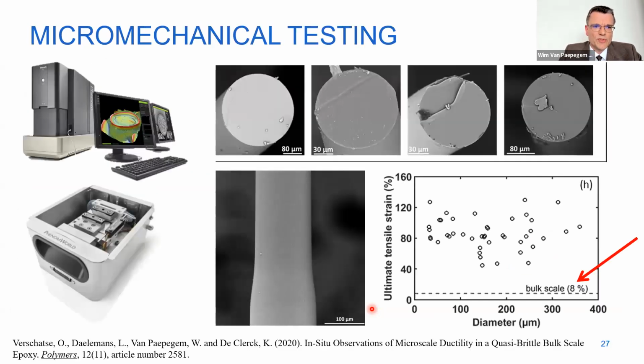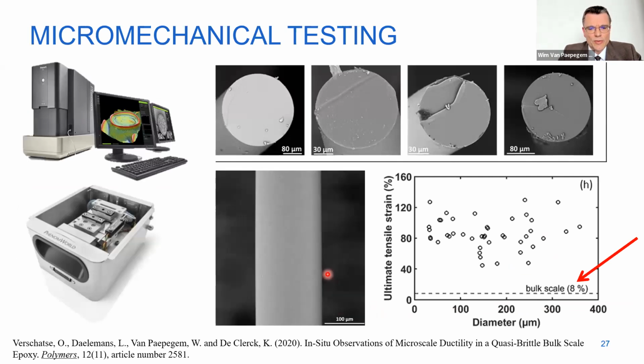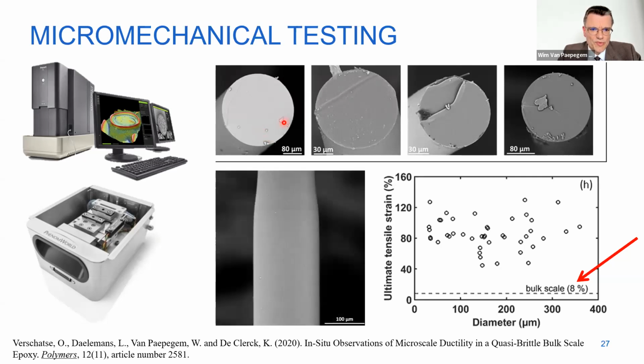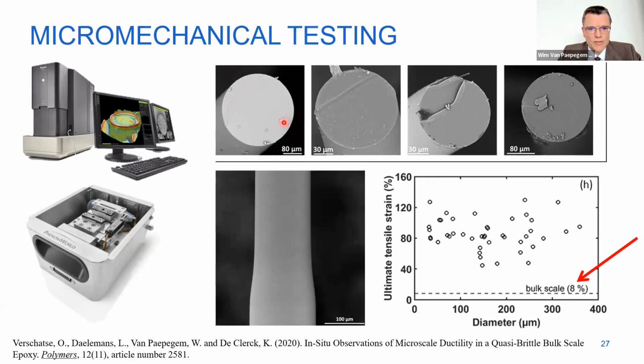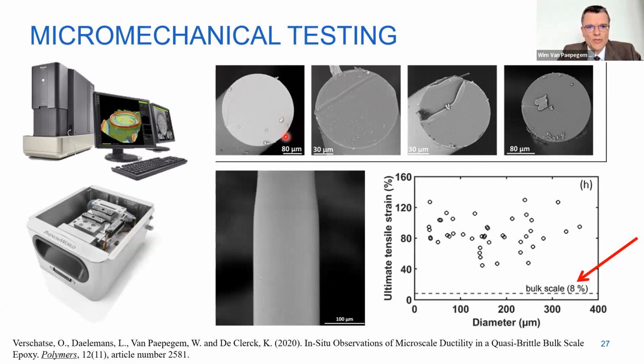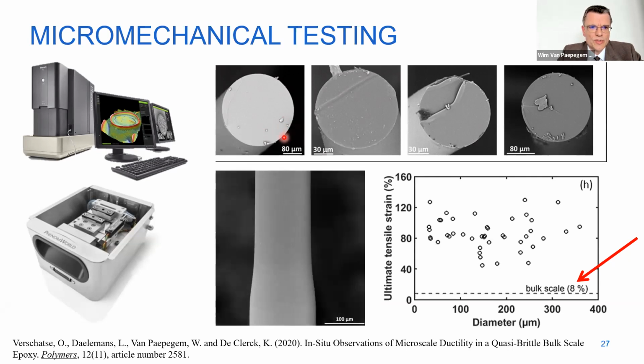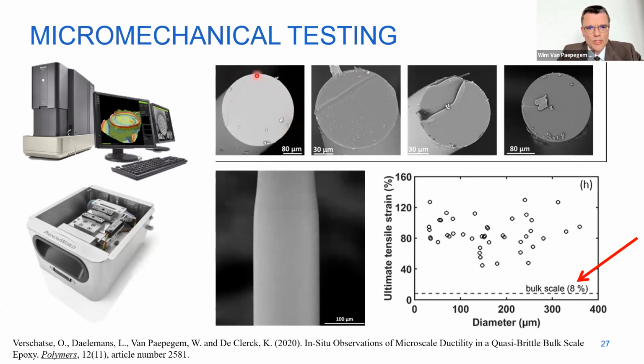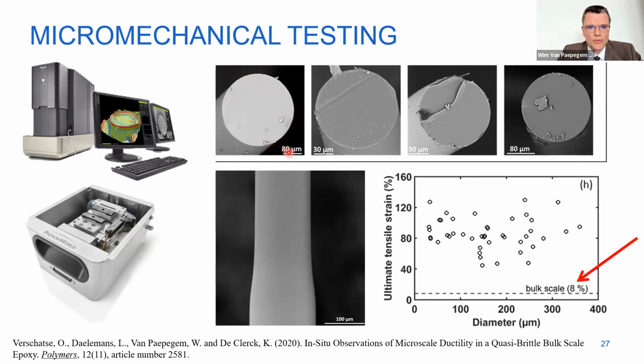First, coming back to this bulk versus in situ properties. Here you see our attempt to shed some light on this. These are pure polymer fibers. So don't be mistaken, there's no fiber reinforcement, but to make the polymer in very thin volumes, we made fibers out of it. So here you see pure polymer fibers. You see the diameter here is very small.